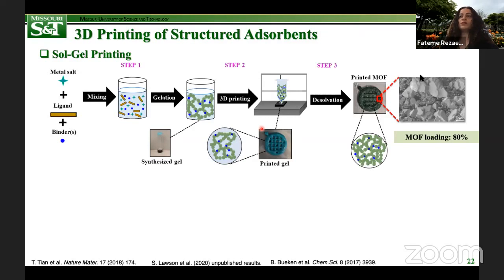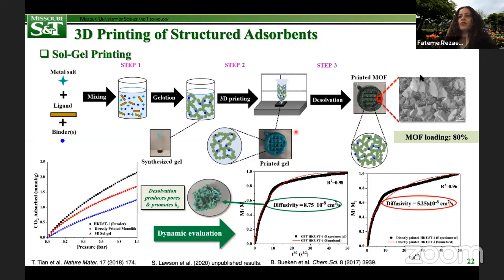This technique has produced interconnected MOF particles whose topologies were consistent with HKUST-1 in the literature, as you see here, with 80% weight loading. The other 20% came from the bentonite or PVA, mainly PVA. And also we investigated the CO2 adsorption performance of these novel sol gel printed scaffolds, and we showed low adsorption, unfortunately, equilibrium adsorption capacity, which was around 60% of the powder's capacity.